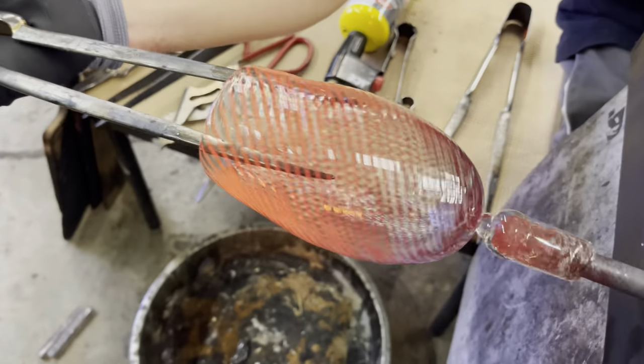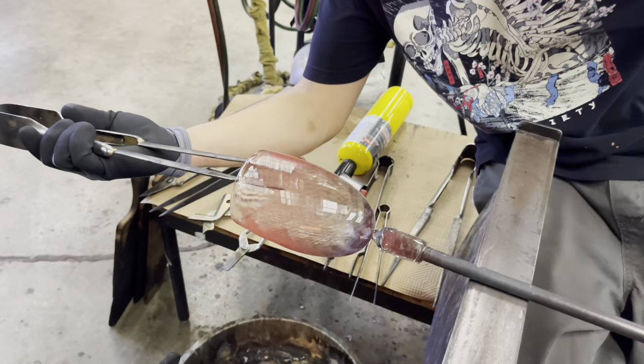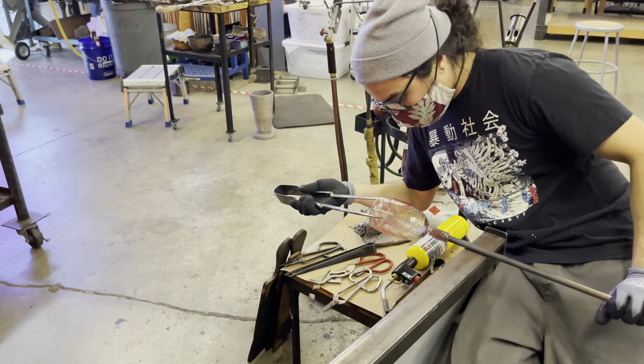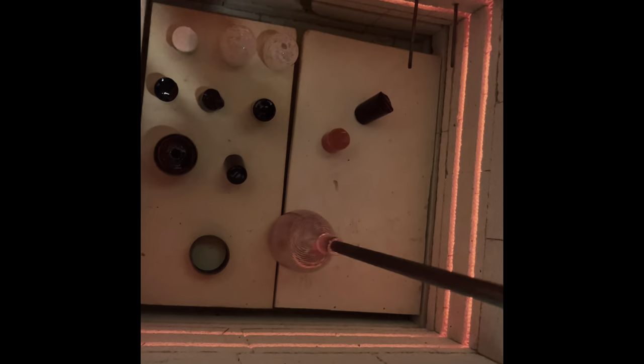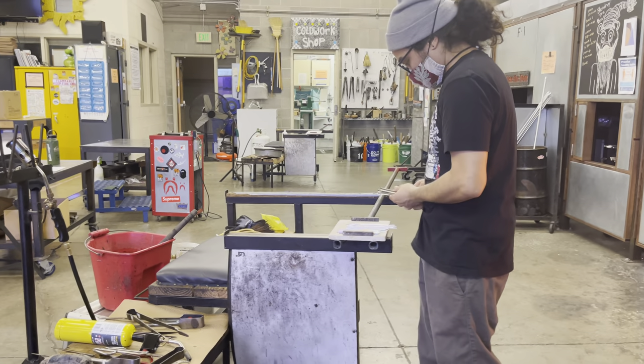Although we're working with black colored glass, due to the heat, everything will turn bright red and orange. With our first cup complete, it is placed inside of an annealer — a temporary warming oven at about 1,000 degrees Fahrenheit. With that aside, we begin to create the second cup, the second pattern.